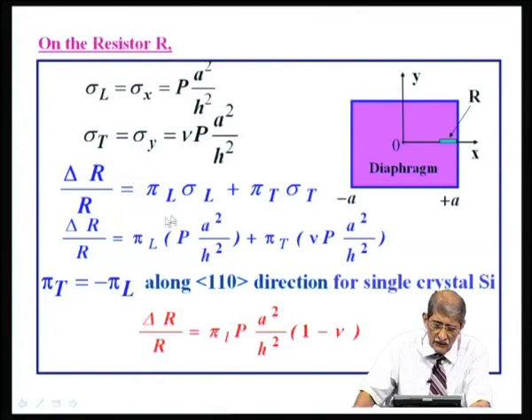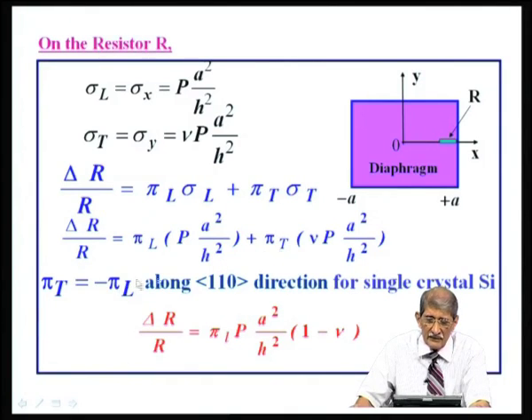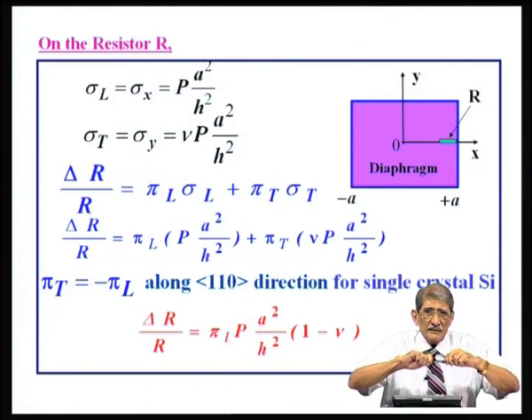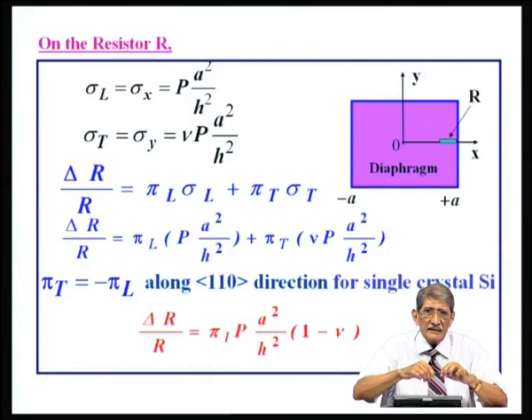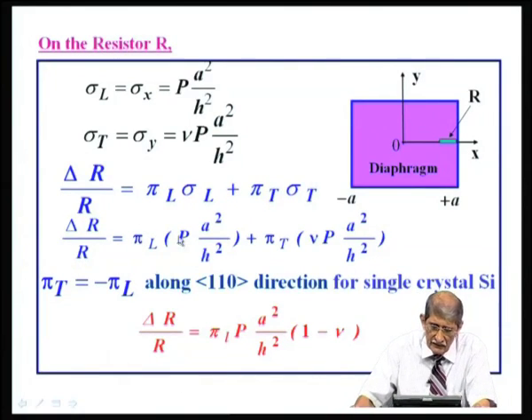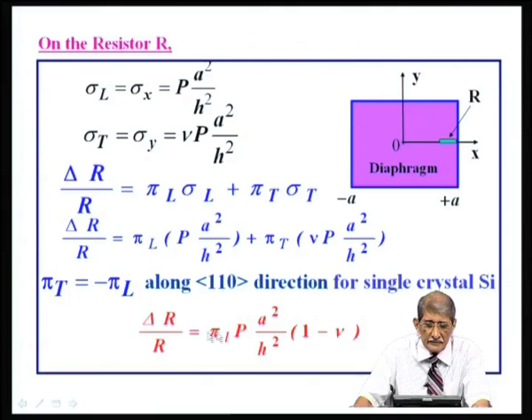Now, delta R by R you can put as pi L into sigma L, which is P into A by H whole squared, plus the transverse stress into nu into P into A by H whole squared. Now, this pi L and pi T are opposite. For a single crystal membrane, pi transverse is the negative of pi longitudinal, because the longitudinal stress will increase the resistance for p type, and transverse stress will decrease it. That is why this negative sign takes care of that. Substituting that, you get delta R by R is pi L into P into A by H whole squared, which is common, and pi L plus pi T, which is pi L into 1 minus nu. So the whole thing is pi L into P into A by H whole squared into 1 minus nu, delta R by R.